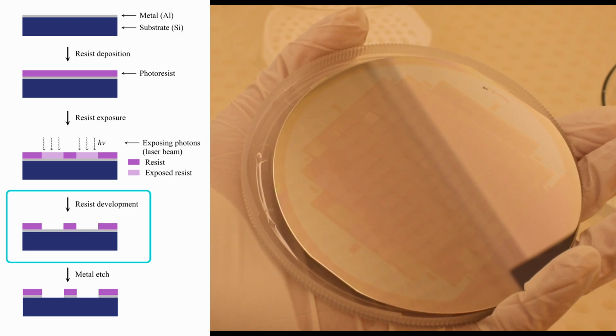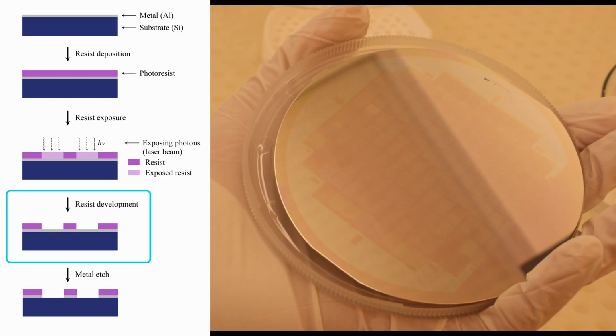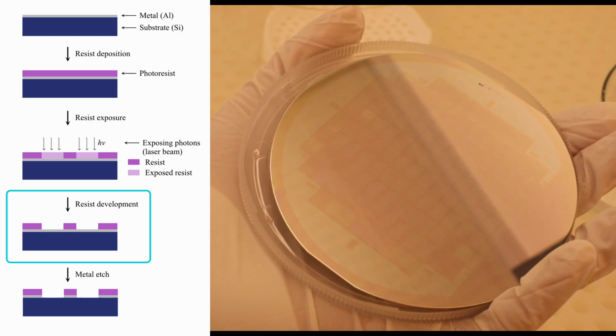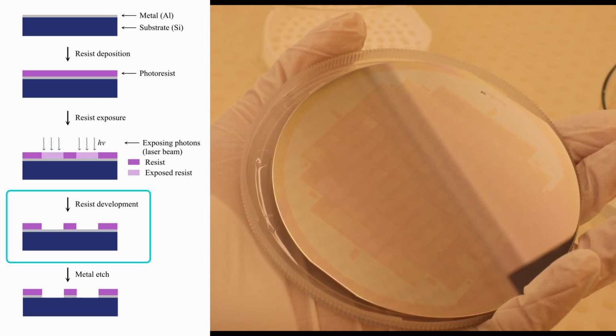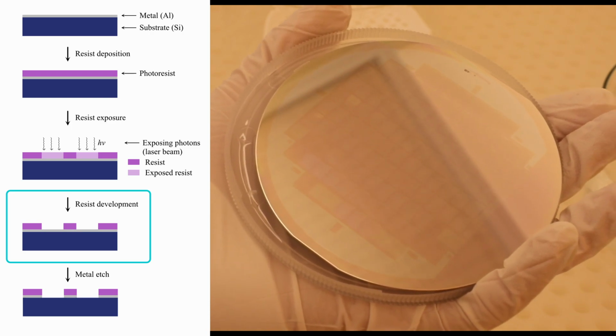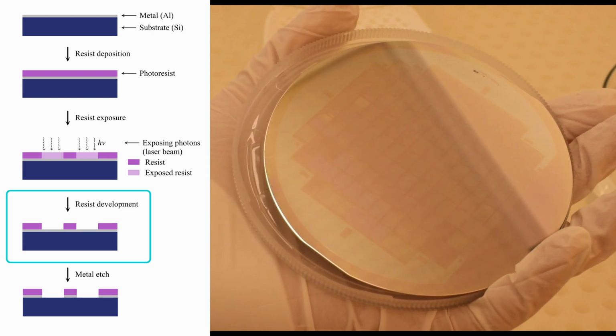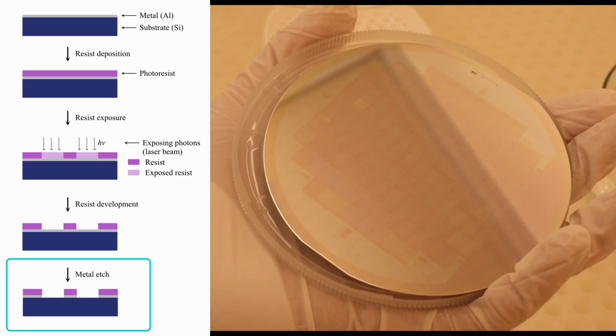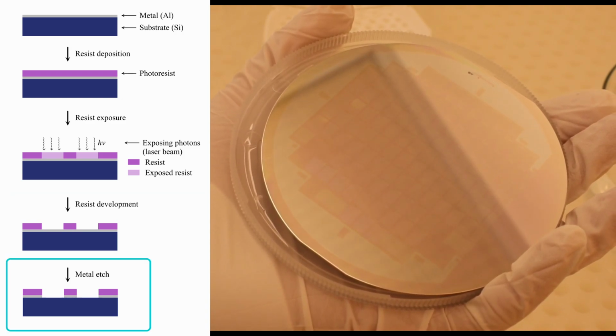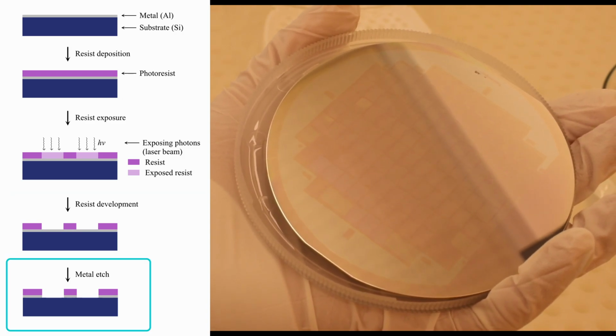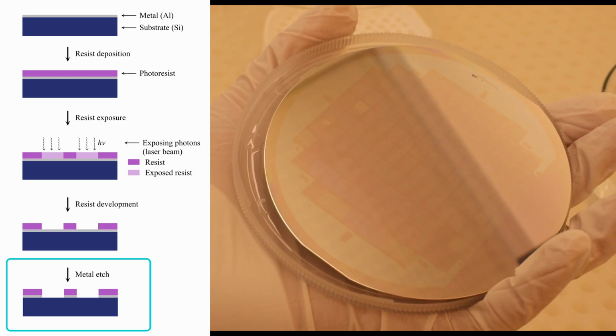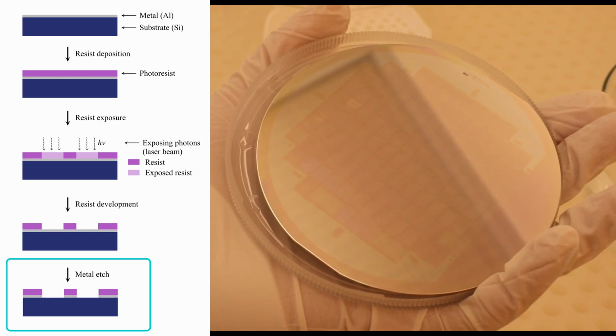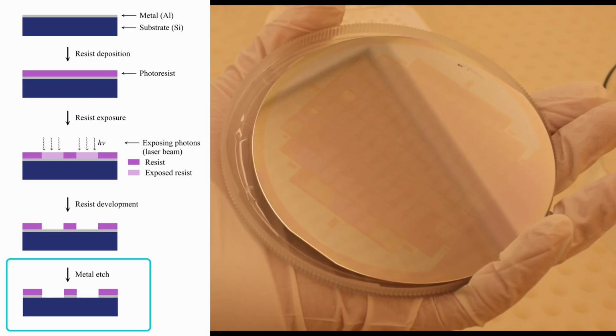Now we can see a faint pattern on the wafer, but remember, the pattern is not actually present in the metal yet. It's only written into the resist layer covering the metal, and the aluminum underneath is still continuous. To transfer the pattern into the metal, we are going to submerge the wafer into an acid which reacts with aluminum. The areas of the metal protected by the resist will be unaffected and will remain on the wafer, but whatever aluminum is exposed to the solution will be removed.